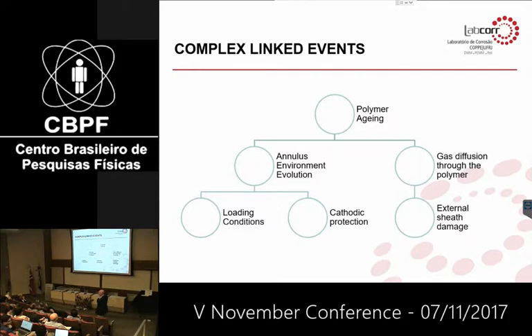There is no number to express localized corrosion because it's not very precise. It's very hard to express in numbers the resistance to stress corrosion cracking or hydrogen embrittlement cracking of a material. So you have to face a chain of very complex events that goes from polymer aging to the annular environment.